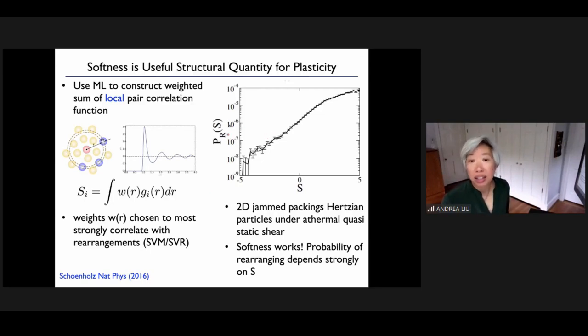And what we see here is that the probability of rearranging as a function of softness is an extremely sensitive function of softness here, varying by over 4 orders of magnitude over this range of softness. This is for 2-dimensional jam packings of Hertzian particles under athermal quasi-static shear. And we see that softness is really an excellent predictor of the probability of a particle to rearrange.